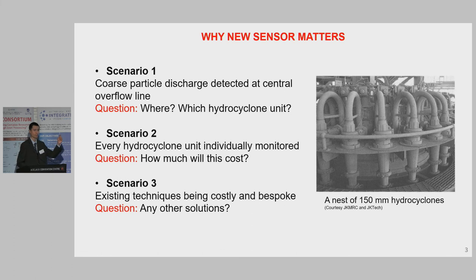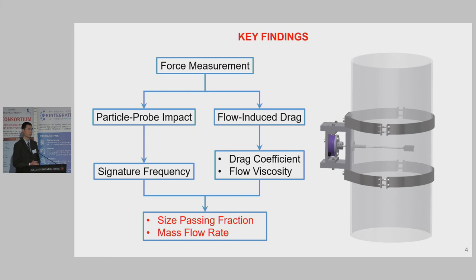The answer is yes, we have a solution for you. In our project, we have developed a force measuring unit with a probe penetrating into the overflow pipe to measure the force from the incoming slurry. We have found the measured force can be divided in two parts. One is the particle probe impact, the other is the flow-induced drag. Further, we have found particles of different size distributions have their unique signature frequencies that are embedded in the particle probe impact events. And size distributions can also be correlated with flow-induced drag in terms of the drag coefficient and flow viscosity. All this information is useful to determine the size passing fraction for target particle size.